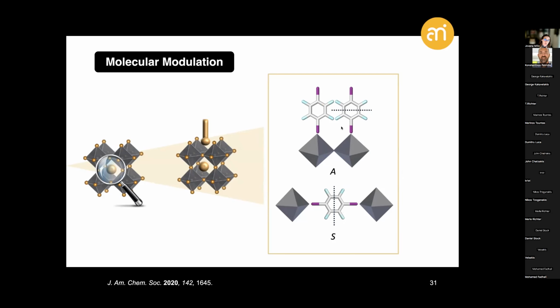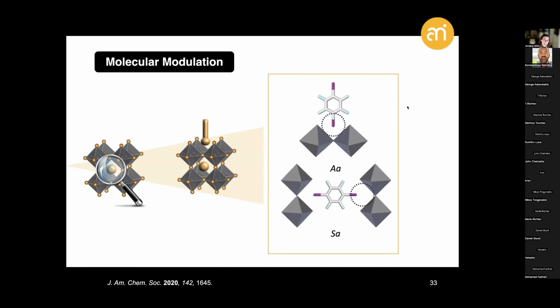Furthermore, this binding can take place through either these halide termini that I highlighted, which is in accordance with the directionality of halogen bonding and will in this case be labeled by the index S, but also looking into the hydrogen bonding interactions that are more common in hybrid perovskite through the A-cation cavity surface. We can also imagine, or at least project, the possibility of having some analogous hydrogen bonding interaction, which will in this case be labeled by the index A.